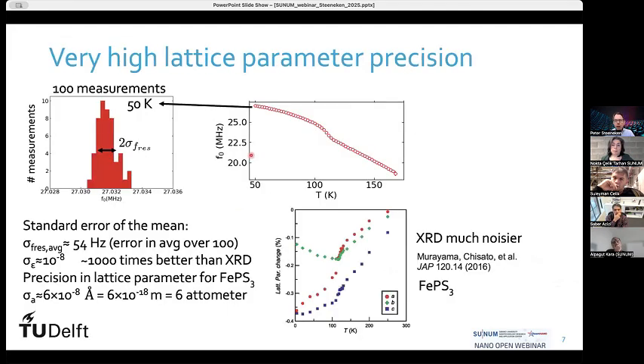One special thing I would like to highlight is that these resonance frequencies are very good measures of the strain and of the lattice parameter of the material. So we can measure this resonance frequency to a very high degree of accuracy. You see that the resonance frequency in this case is 27 megahertz, but the variation in it is very small. It's only about 54 hertz. That means that we have an accuracy of 10 to the minus 8 in the stress and the strain that we measure, which is much better than other techniques like X-ray diffraction.